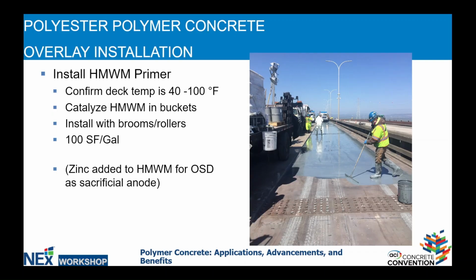The typical coverage rate is about 100 square feet per gallon, and if necessary for orthotropic steel decks, we can add zinc to the high molecular weight methacrylate primer, which will act as a sacrificial anode and prevent, control and mitigate corrosion.